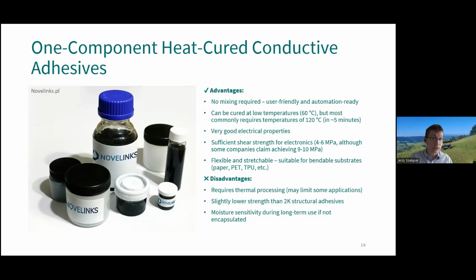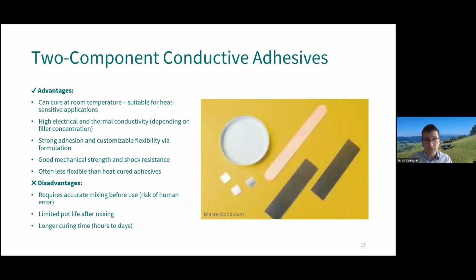Anyways, in rigid electronics, curing at 120 or even more degrees is very common. The issue is with bending, even more with stretching. But most of the materials proposed for flexible uses, especially the ones actually working, are one-component heat-cured adhesives. Concerning electrical properties, these are the adhesives with the lowest resistivity. But the curing temperature still can be an issue. Also, shear stress resistance may not be enough.